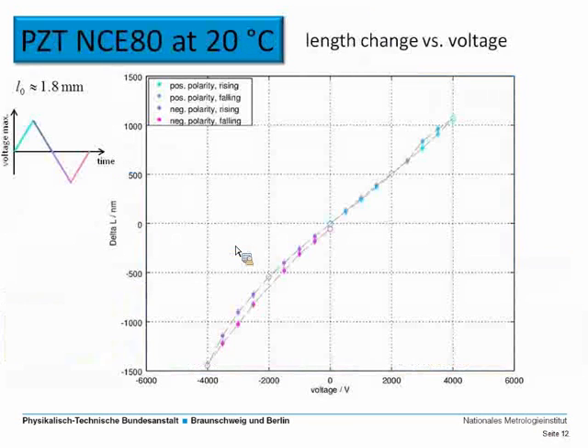So let's start with something really basic. PZT NCE80 at room temperature, 20 degrees. The initial length of the sample was something like 1.8 millimeters. And here the length change relative to the initial length is shown as a function of voltage. So we start here at 0, then ramp the voltage up and see that the sample expands, ramp the voltage back down, see that it goes to 0 again, switch the polarity, go to some maximum value of the voltage, and go back to 0 again.